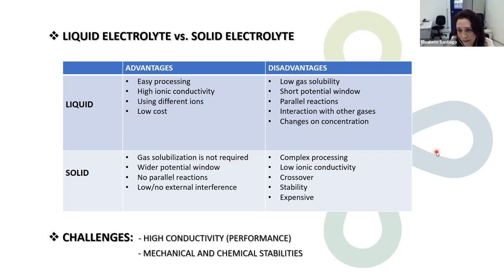In addition, you have an interaction with other gases, which is very important when you use electrochemical reactors based on gas conversion. And you have changes in concentration that need to be recovered over time, so you have to adjust the concentration over time. In the solid electrolyte, gas solubilization is not required, because the gas goes directly to the sites of the catalyst, okay? And a wider potential window is obtained here because you don't have parallel reactions. I mean, you have some parallel reactions, but less than in comparison to liquid electrolytes. So there is low or no external interference, for example, from CO2.